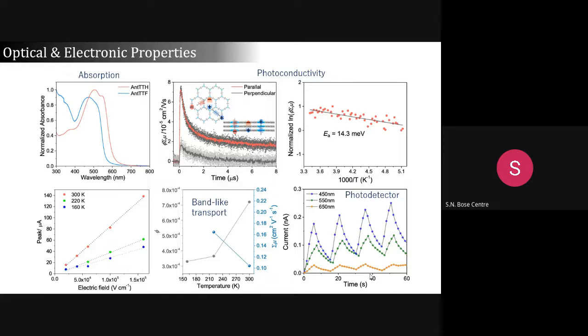Initially we can see from this plot there is a very minimal slope. As you know, there are two types of transport: one is band transport, another is hopping transport. In hopping transport, there will be several trap sites where, once you excite, the electron will hop from one to another with thermal energy. But in band transport, because of phonons, you may not be able to transport your charge carrier at higher temperature, because phonon vibration and phonon scattering will come into action, and you see decreasing charge transport with increasing temperature. Here we calculated the charge carrier generation yield, and from that we calculated the conductivity. For this system, with the decrease in temperature, we see an increase in conductivity, and it also has a good photodetector ability.